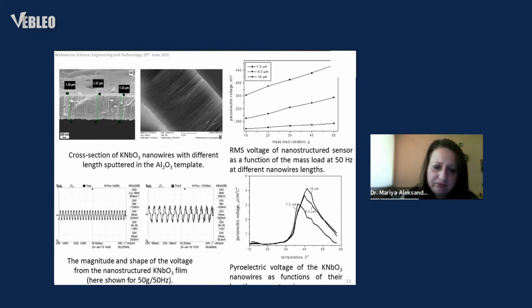So we found that the pyroelectric response is not so sensitive to this nanopatterning, but it could provide a measurable pyroelectric voltage with a sensitivity of 400 nanovolts per micrometer, and it is active in the temperature range really close to most of the human-interest applications, 30-40 centigrade, making it suitable for healthcare applications, body temperature change monitoring. So to the best of our knowledge, this is the first time of a multi-sensing device involving a combination of these materials.